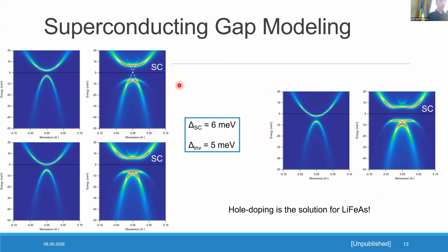And we consider three cases: when the upper band is above the Fermi level and the lower band is below the Fermi level, then when the upper one touches the Fermi level, and the last case is when the upper band is slightly lower. If they are on different sides of the Fermi level, superconductivity tears it apart, and surface states are expected to be quite distinguished. Ideally, we want the Dirac cone to be exactly on the Fermi level. But the moment the upper band touches the Fermi level, the inverted gap is, first of all, moved farther away from the Fermi level, and secondly, it gets squished by superconductivity.